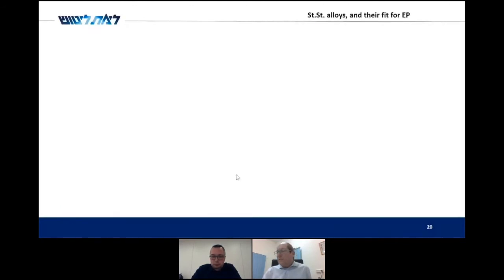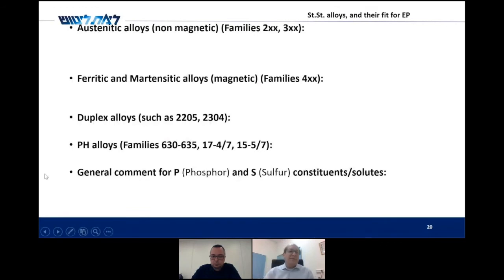As Professor Groysman mentioned earlier, there are all sorts of stainless steel alloys. These are the 5 families, or 4 of the families that he mentioned: austenitic, which are not magnetic; ferritic and martensitic, which are magnetic; duplex, which are a combination of austenitic and ferritic; and PH, which are precipitation hardening, and they all have similar but different electro-polish behavior.